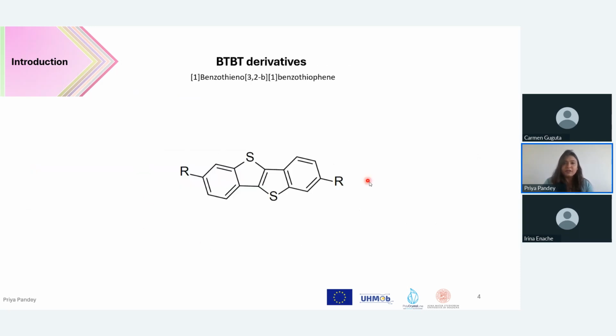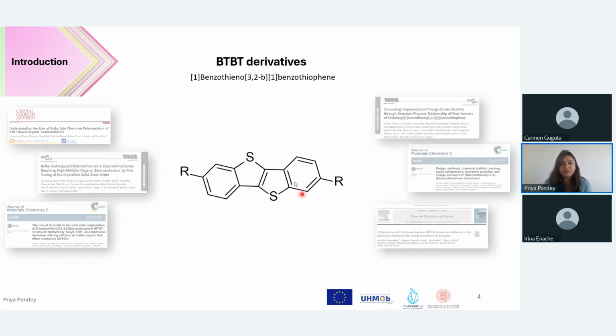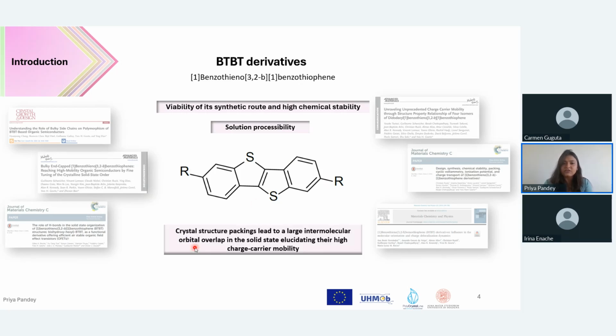As Carmen mentioned, I mainly worked with the BTBT derivatives. This is the BTBT core, and in the past few decades there has been a lot of research published with these kinds of molecules, which were functionalized mainly at the 2 and 7 positions. The reasons for selecting this molecule are the viability of the synthetic route, high chemical stability, the solution processability of this molecule, and the crystal structure packing that leads to a large intermolecular orbital overlap in the solid state, which leads to high charge carrier mobility.